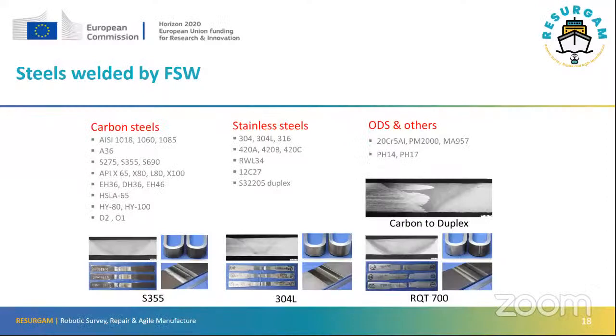In terms of the different grades of steel that can be welded, we're finding that we can weld almost any grade of steel because we're not melting anything. We're not changing the composition. And so even some grades of steel, which are considered very, very difficult to weld by conventional techniques, we can weld by friction stir. For example, we can weld a carbon steel to a stainless steel without problems, which is very difficult to do by other techniques, but friction stir can do that.